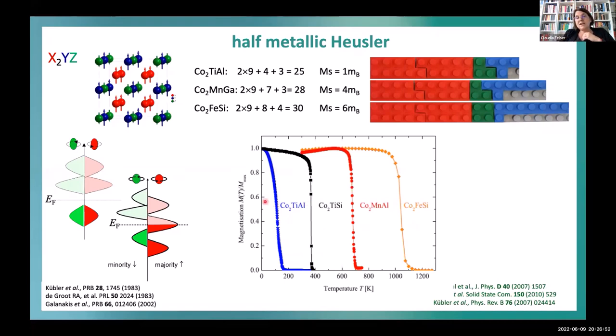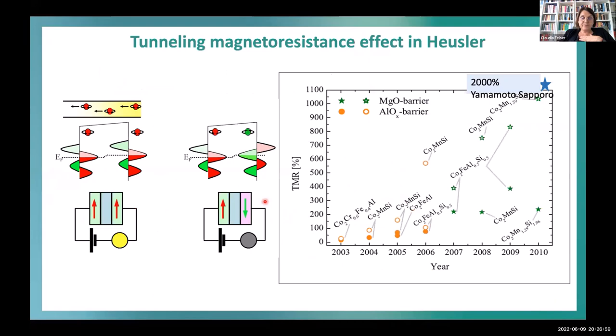And this is a nice thing why we all like Heusler compounds, because they are then also useful for room temperature application. So I'm interested in Heusler compounds since a long time, and this makes the bridge now to spintronics. Because the half metallicity was also interesting in the context of the tunnel magnetoresistance effect and the GMR effect. So you can simply align the Heuslers in the same direction, then you get a low resistance. And if you align them in different directions, so if the magnetizations are aligned like this, then they have no states to go, and we have a large magnetoresistance effect. And this is the reason why we have this large tunnel magnetoresistance effect in a very simple picture.